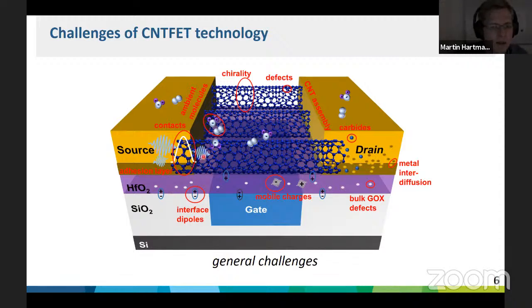One thing is the contact, the source and the drain contact. So you would like to have here a really small or an almost vanishing barrier. And this is quite difficult to achieve. In literature, you read quite often, okay, use palladium as a contact material and you get ohmic contacts. But this is not fully true. And there's one issue with palladium. Palladium doesn't stick properly on oxides. So you always need an adhesion layer.